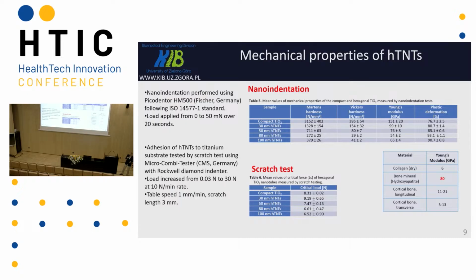Then we carried out the nanoindentation test and scratch test to check the mechanical stability of this nanostructure and to confirm if our idea was correct. So, as you can see, the hexagonal titanium dioxide nanotubes reveal a Young's modulus very close to the Young's modulus of bone mineral. This nanomodification also decreased the hardness, never mind if we talk about Martens or Vickers hardness. And what is also important, hexagonal titanium nanotubes revealed higher plasticity when we compare it to compact TiO2.